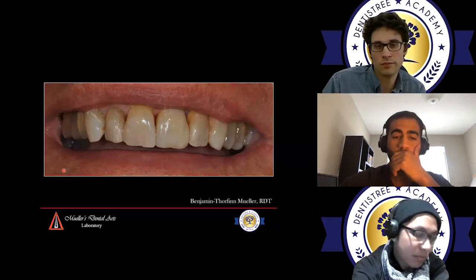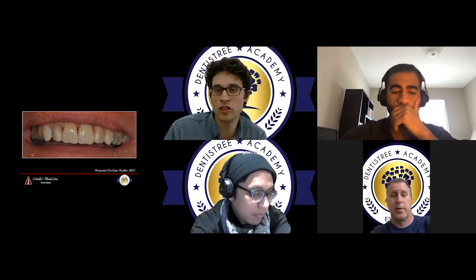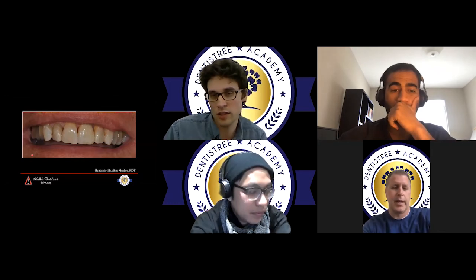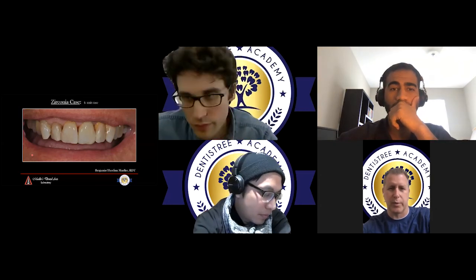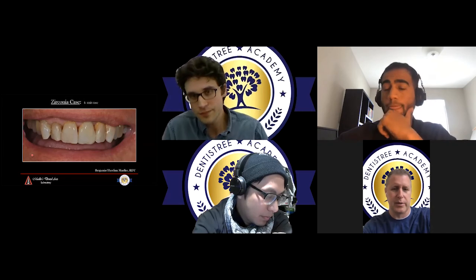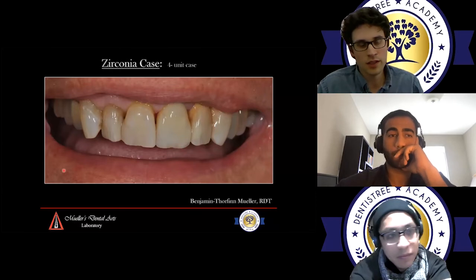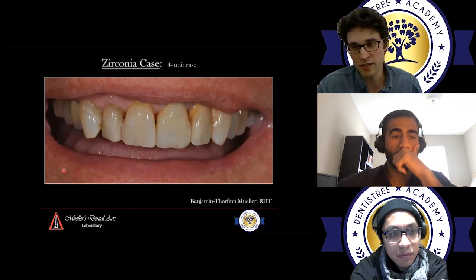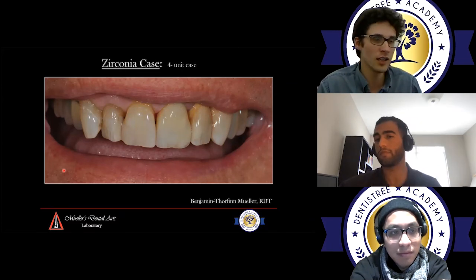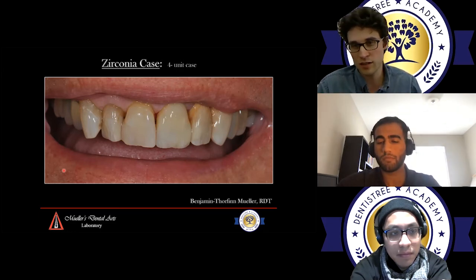We have done a handful of cases where, for whatever reason, we have engaged the tooth-born bite as well. Sometimes you have to be willing to take some risks and try different things, as long as it's informed consent and the patient understands what we're doing — that it's not necessarily textbook, and that's okay. Don't be a cowboy, but if you want to try something and the patient understands, there's no problem. As another example, with lithium disilicate it's contraindicated for posterior bridge work, but if you have oodles of room — two-plus millimeters occlusally — and the connectors and crown walls are super strong, you can get away with it, especially if it's not a bruxer.